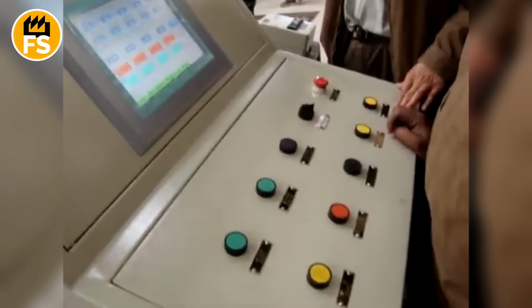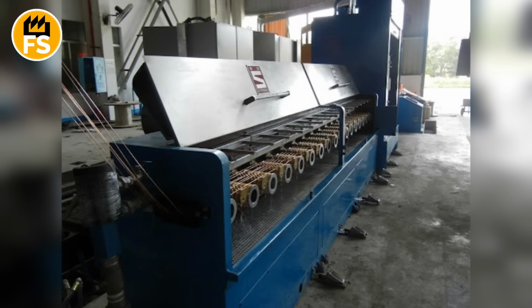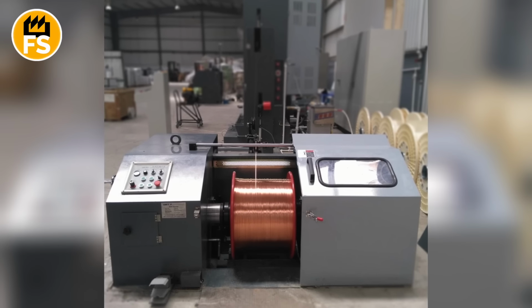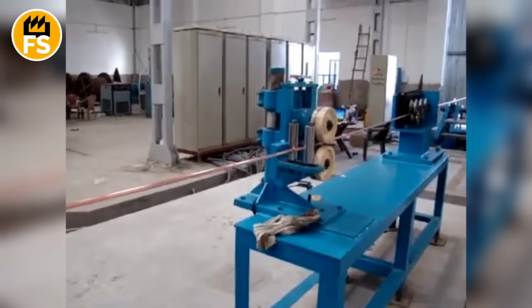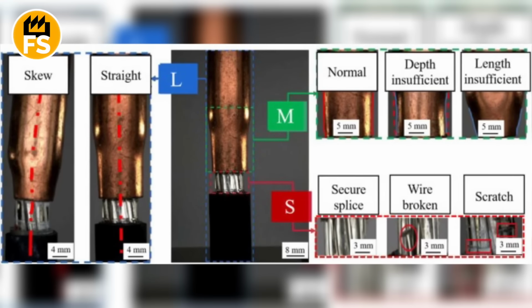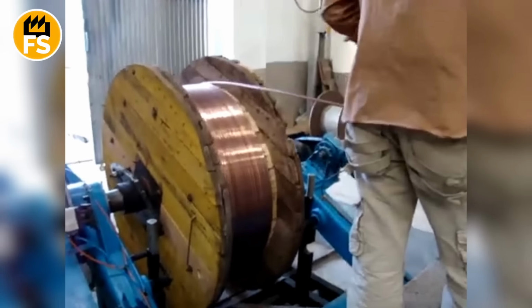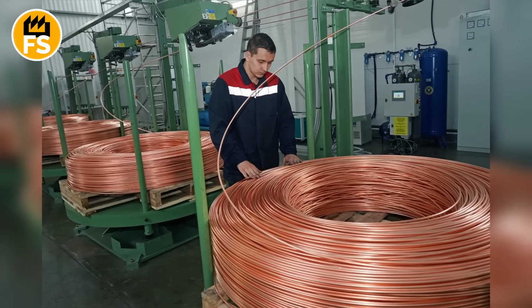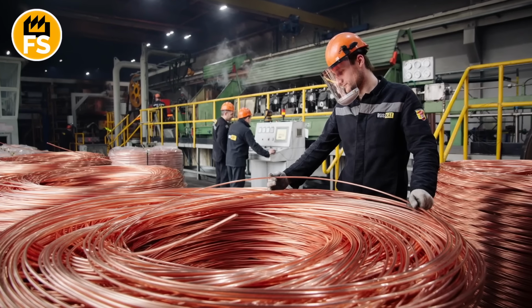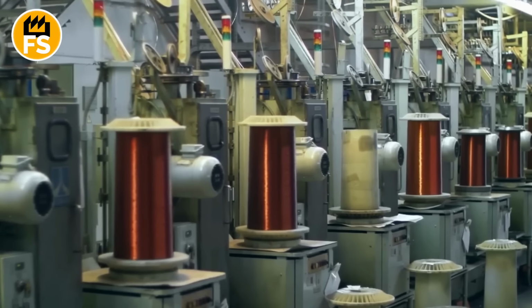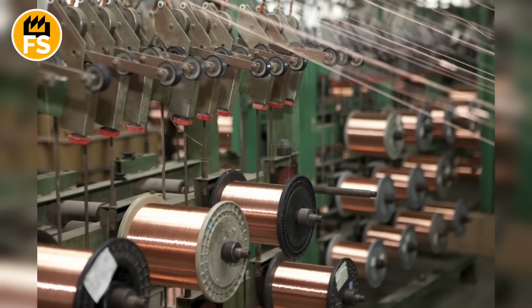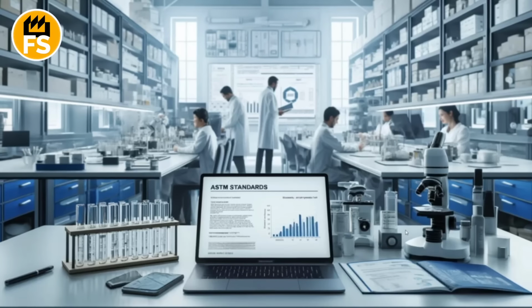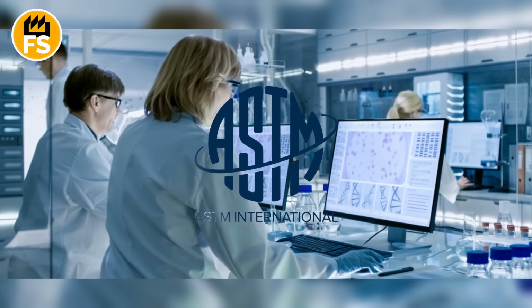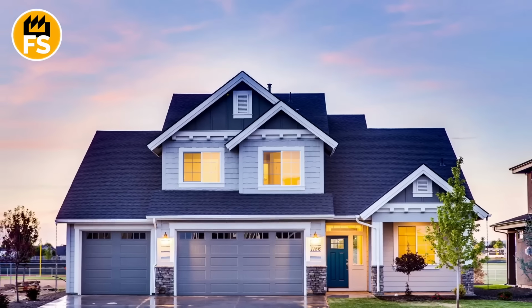Each stage of drawing is strictly controlled. The diameter is measured by laser devices. The feed speed can reach 100 feet per minute and is automatically regulated. If defects appear, such as scratches, irregularities, or cracks, the process is stopped for correction. The finished wire undergoes a final quality control. Not only the geometry is checked, but also the electrical properties. The resistance must not exceed a certain value per 1,000 feet of length. Conductivity, mechanical tensile strength. All parameters must comply with strict American Society for Testing and Materials standards. After all, this wire will become the basis for cables that will transmit electricity to homes, offices, and factories.